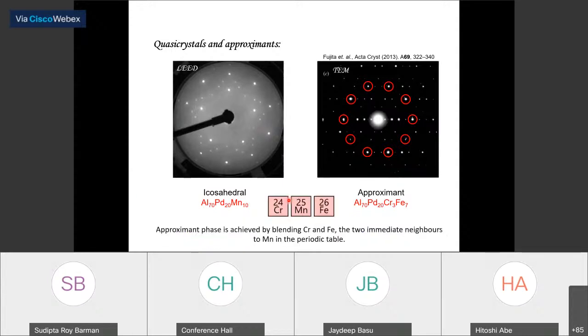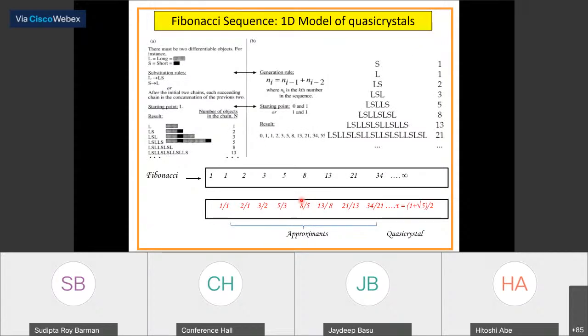And for example, we studied these approximants where we have aluminium, palladium, and the manganese of the quasicrystal has been replaced by chromium and iron. So chromium and iron, as you can see, are the two elements on the two sides of manganese in the periodic table. In this way, we keep the e/a ratio similar between the quasicrystal and the approximant. The e/a ratio has important significance in these systems in the stabilization of these materials.